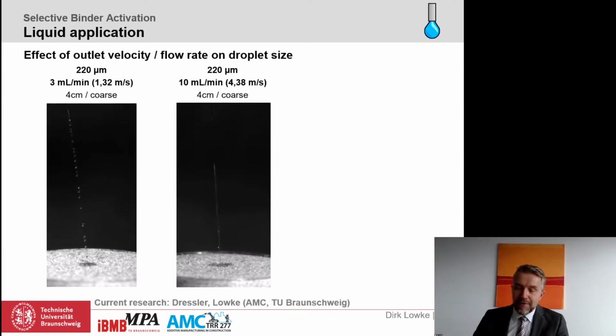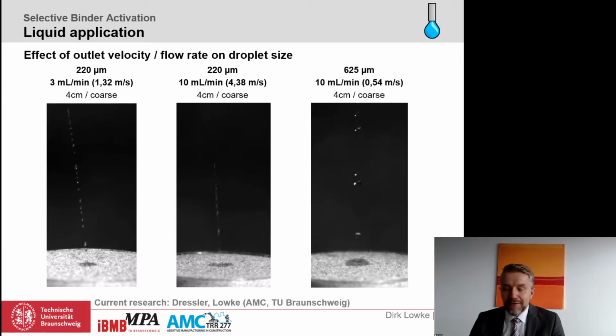In the last scenario, we have now increased the diameter of the nozzle to 625 micrometers while maintaining the same high flow rate of 10 milliliters per minute. And now you can see the water form droplets again, but now with a larger diameter. As you can see, there's a complex relationship between nozzle diameter, flow rate, and the shape of the water jet.